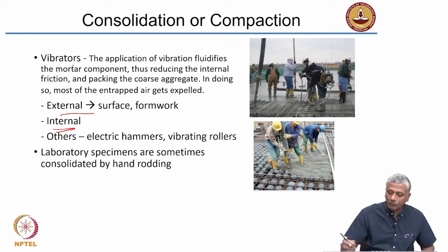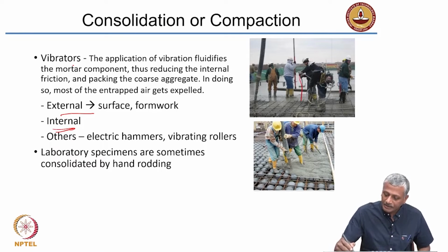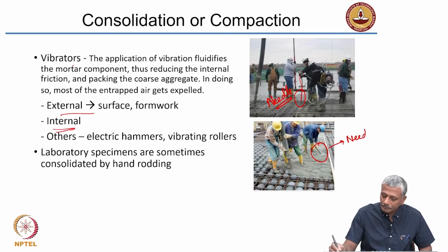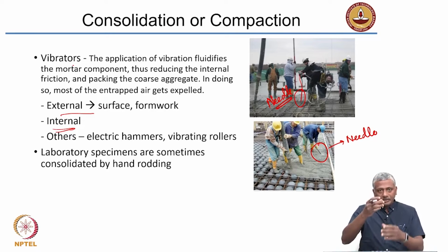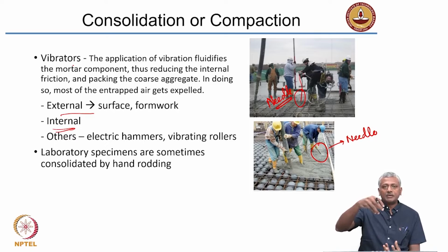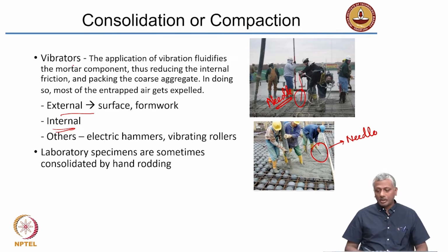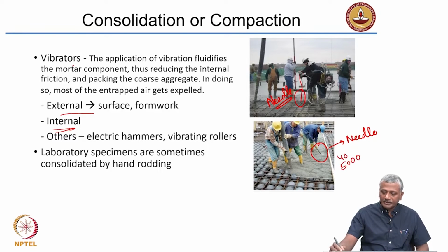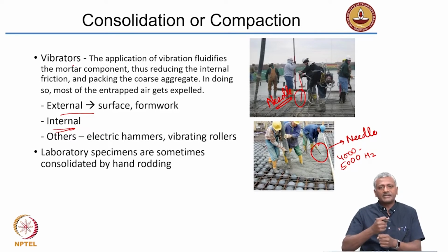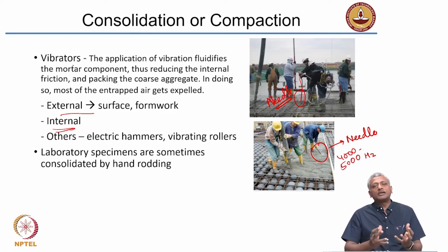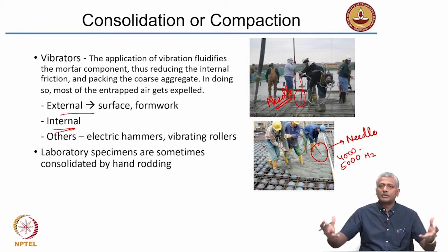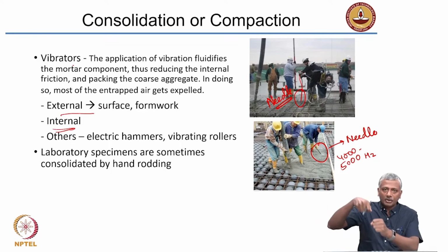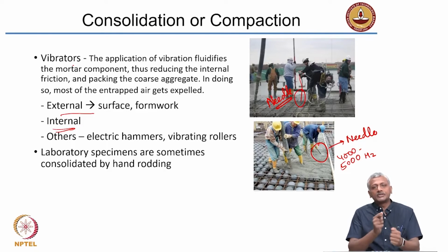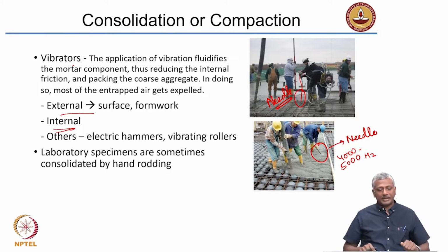Or you can have an internal vibrator, like what these people are doing. You see that this guy is holding a needle, that's a needle vibrator. It's a vibrating needle again here. So a needle vibrator basically is a rod of steel, which is being made to vibrate at a very high frequency. We are talking about 4000 to 5000 hertz. This vibrates at a very high frequency. So what it does is it loosens up the concrete so that it starts flowing. Concrete which is very stiff, if it's dumped into the formwork, will not go anywhere. But as soon as you put your vibrator inside, which is vibrating at such high frequencies, it loosens up the aggregate and then starts the concrete to flow, and that creates the compaction.